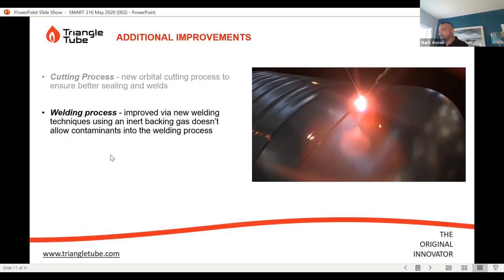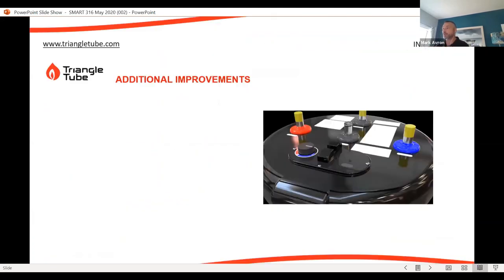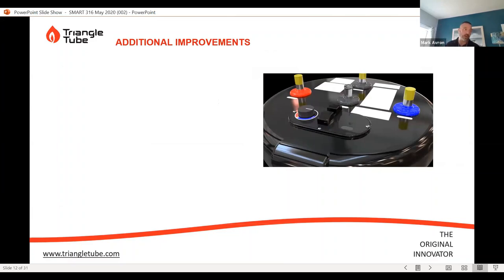The welding process has been improved too, by using backing gases in the welding process to prevent contaminants from getting into your welds, which become weak points. Going to a better welding process has reduced the risk of having an issue with the seams. You've got the material, and then you've got seams, or anywhere we're cutting material and adding welds to it. Those tend to be weak points, so we use the best processes and techniques available when manufacturing.